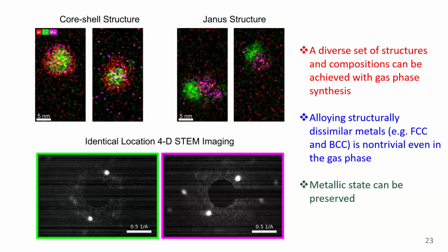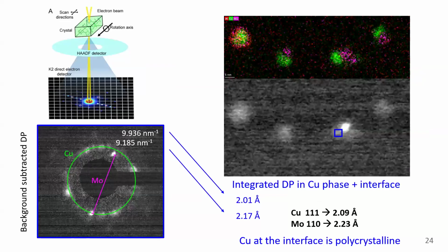It's going to depend on what materials you're using. And so in this one, actually, the aluminum segregates to form an aluminum shell. And so that stabilizes the particle. And so you can see that these are metallic phase. If I go to here, if you look at the electron diffraction pattern, you can see that the copper and the moly are preserved in the metallic phase. And I think that's because there's an aluminum shell which passivates the particle. The aluminum would be oxidized, but that preserves the core.